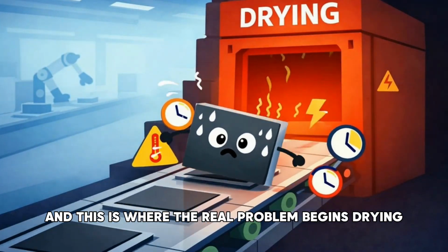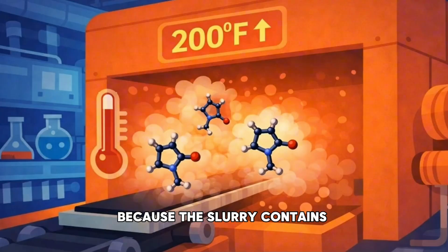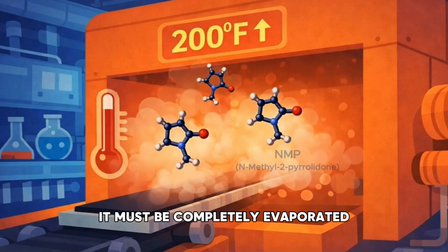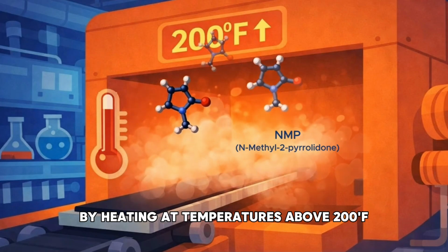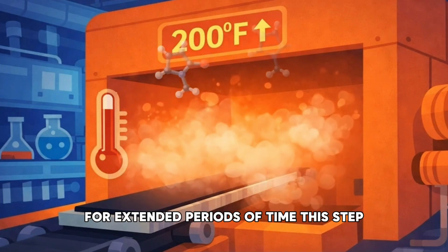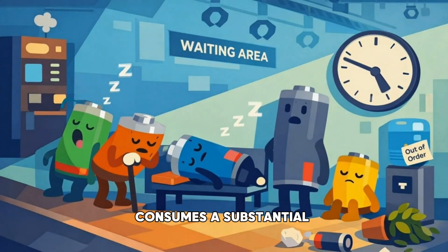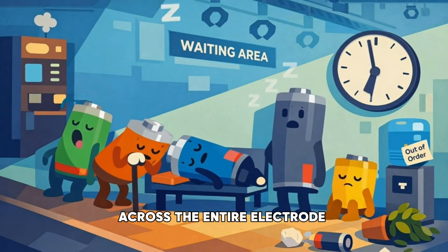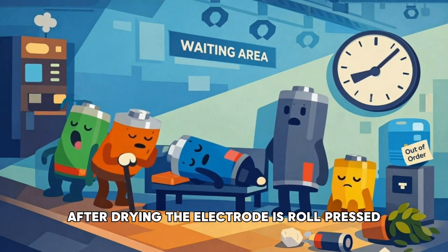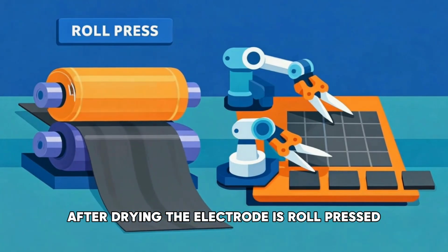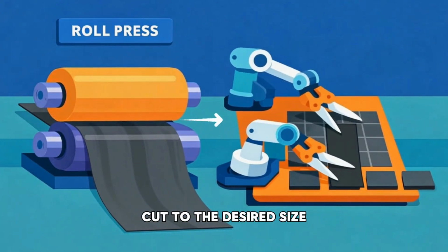And this is where the real problem begins: drying. Because the slurry contains organic solvents like NMP, it must be completely evaporated by heating at temperatures above 200 degrees for extended periods of time. This step consumes a substantial amount of time and energy across the entire electrode manufacturing process. After drying, the electrode is roll-pressed to increase density and then cut to the desired size.